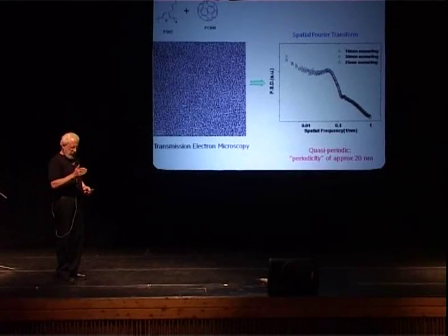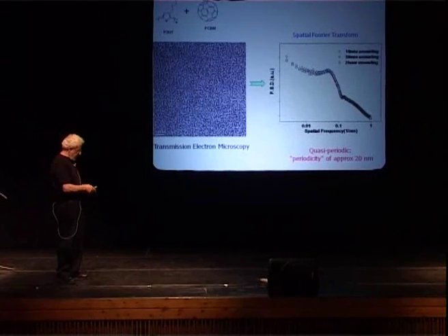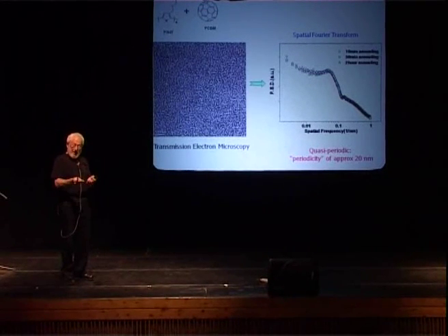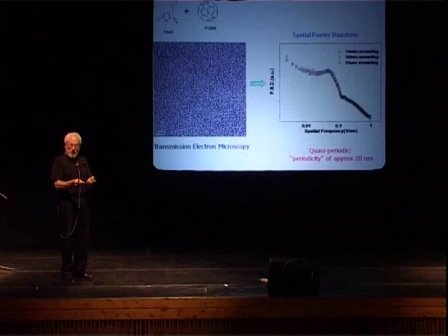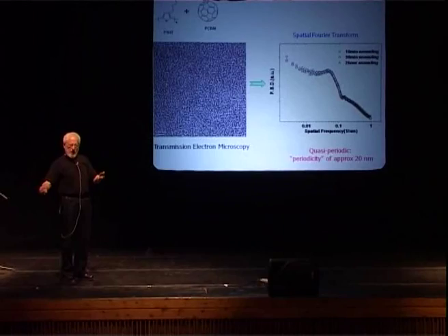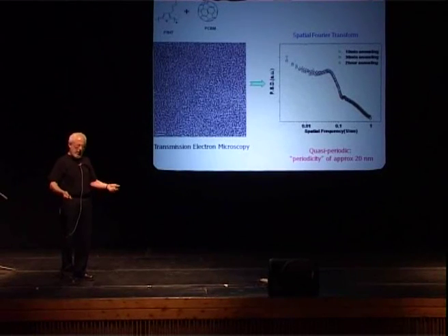if a photon is absorbed at the center of, say, the polymer domain, then the excitation can get to the interface before recombination, and you can get charge separation, and then you've got the hole on one side and the electron on the other side, and you can sweep them out and go forward.